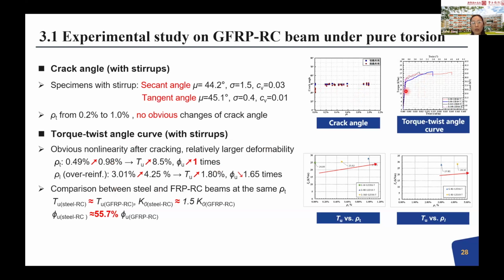For the torque and twist angle behavior, we can see that with the increase of the stirrup ratio, the deformation will increase. We also compare with steel, showing the comparison of steel and FRP-RC beams with the same stirrup ratio. First, this is a concrete crushing failure, and we reach a similar torsion capacity. Also, because steel has a larger shear modulus, as I mentioned before, the stiffness is higher than that of the FRP-RC beam. This is very easy to understand. But when we consider the twist deformation, we found that the steel RC beam is lower than the FRP-RC beam.